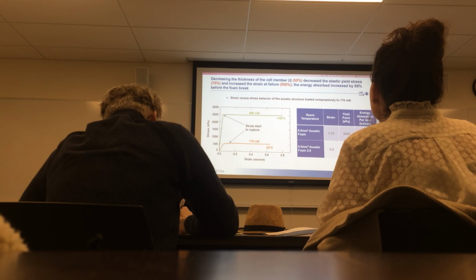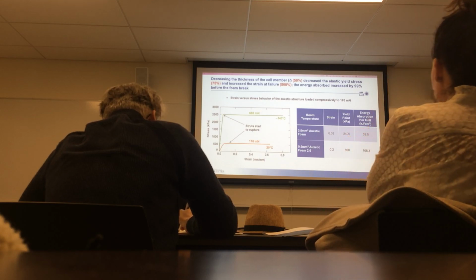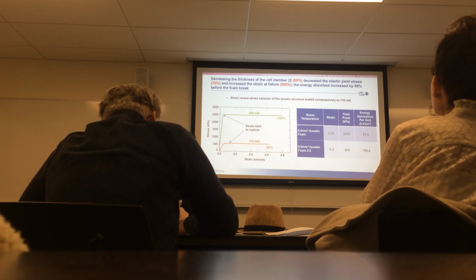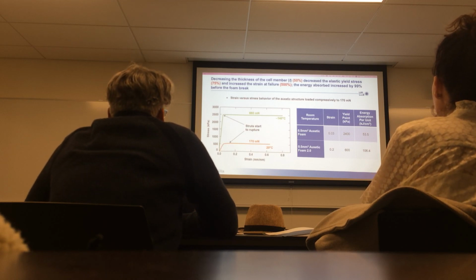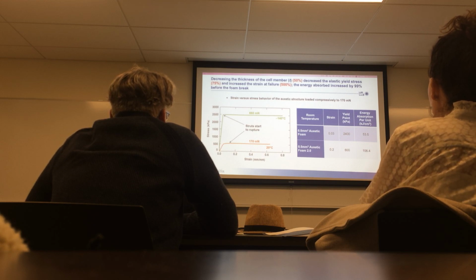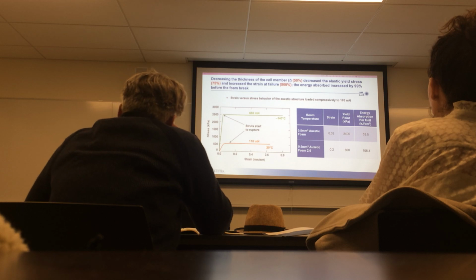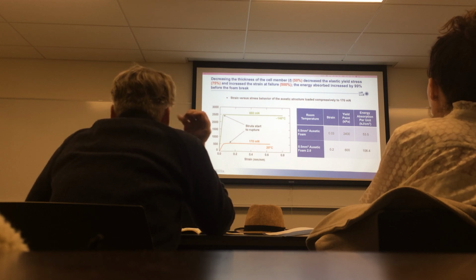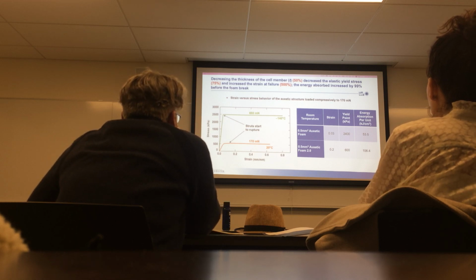After we decreased the thickness, the elastic modulus definitely decreased a lot, and the yield stress decreased, but the strain at the yield increased 500%, and the total energy absorbed before the foam broke increased 100%. That's a very remarkable result. That means our second generation foam structure absorbed more energy than the first generation foams.